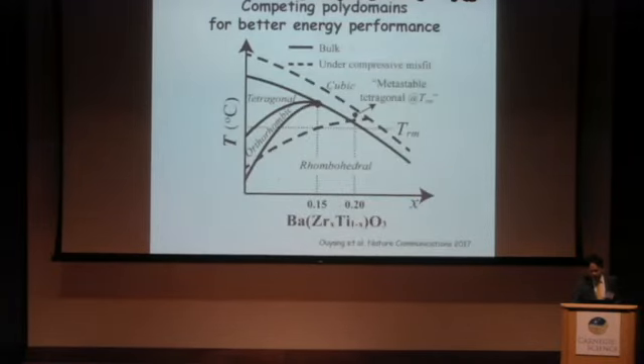Let me just show you here. You can see when you dope with zirconium, actually you change the ground state from tetragonal to rhombohedral, right? Then when you put on the substrate, it likes to be tetragonal because of the symmetry of the in-plane compressive stress. That's how we stabilize the tetragonal phase in the film. But when you grow really thick, the stress more or less relax, you're going to have those hierarchical polydomain structure of the rhombohedral ground state phase.